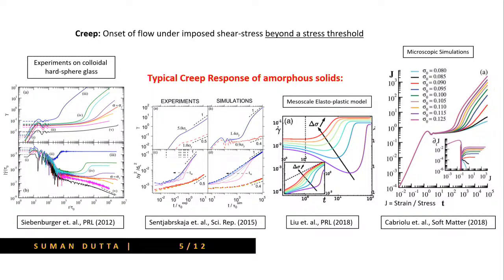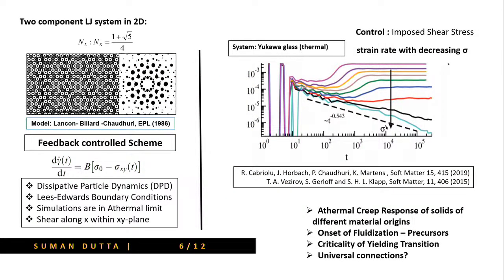This is from some experiments, and people have also compared experiments and simulations, but the microstructural changes when things yield are mostly not well investigated for athermal materials. So athermal creep has been quite open to understand. We studied this using a framework of molecular dynamics simulations. This is a first-principles approach to address this kind of problem, and the framework was developed in this work, where the athermal creep and this kind of power law creep has been seen for the Yukawa glass.